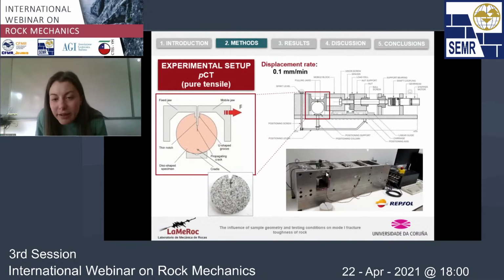So you can see here that we have some strain gauges attached to the device, and we use these gauges to measure the strains during testing, because we wanted to make sure that for the PCT experiments, the device was stiff enough. So in this case, we did it. We analyzed the results of the strains at this location, and we concluded that the device was over-dimensioned. And thanks to some colleagues here at the group of structures, they helped us to create a numerical model of the device, and we could also check with this model, using the finite element method, that the device was stiff.